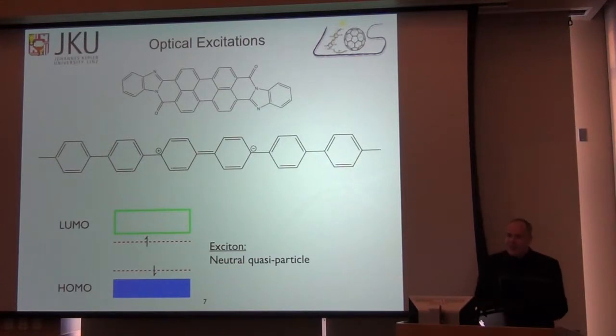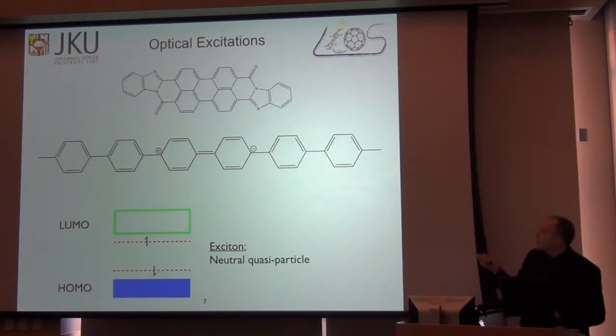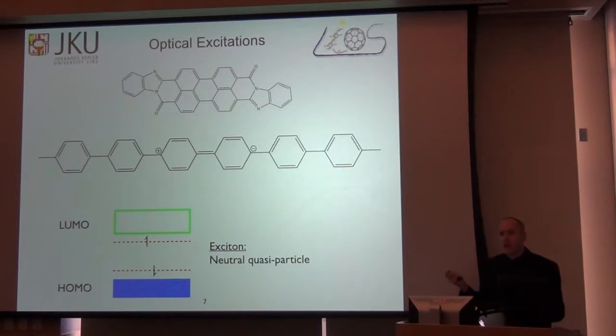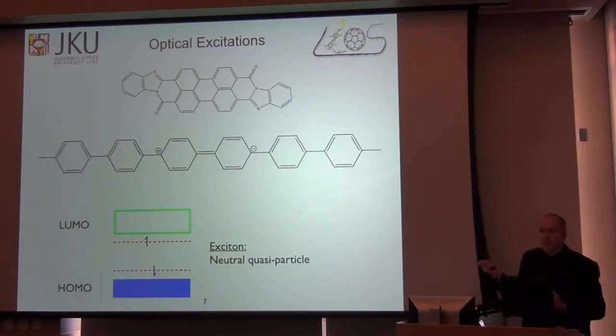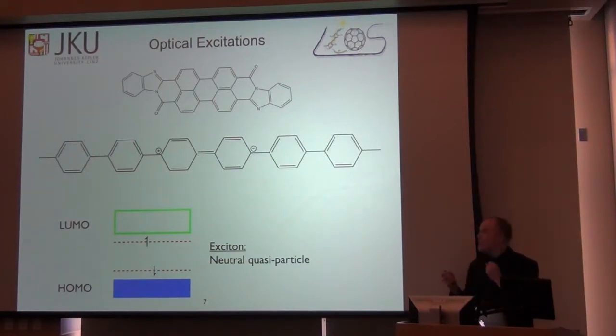So when we shine light into these materials and rearrange the distribution of these pi electrons on the molecule, for a small molecule it's pretty evident that we rearrange the distribution, but we don't really create a charge on that molecule. We just redistribute the electron density. And since these molecules are very small, roughly 1 nanometer in the longest direction, the positive charge and the negative charge feel the influence of each other very strongly.